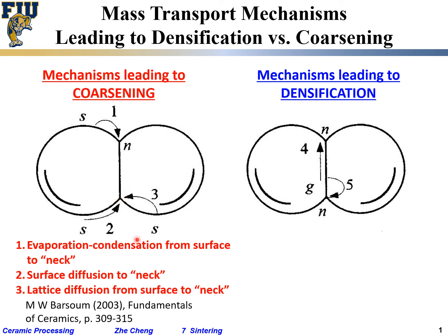What people find is that all three of these different mechanisms only lead to coarsening — they make the particles larger, but don't make the pores disappear. They just try to make sharper tips smoother, no longer sharp. But there's no reduction in the distance from the center of one particle to the center of the other. You can imagine having a lot of protrusions; in the end all those protrusions are gone and the surface becomes flat, but the center-to-center distance remains.